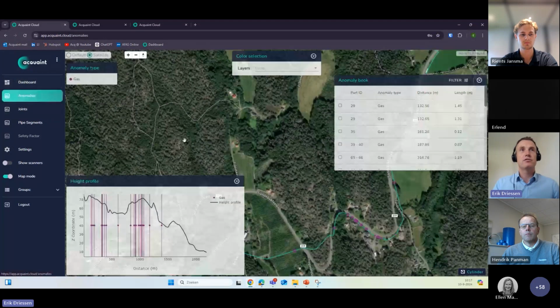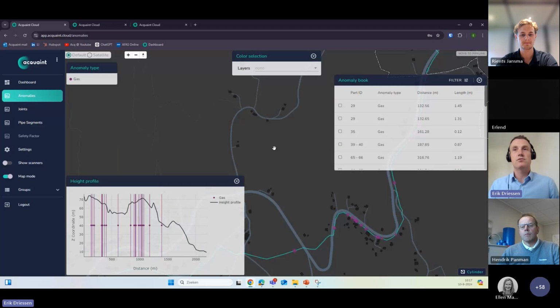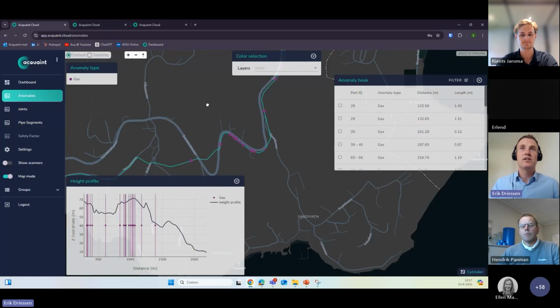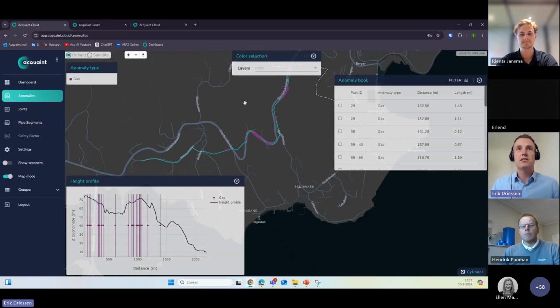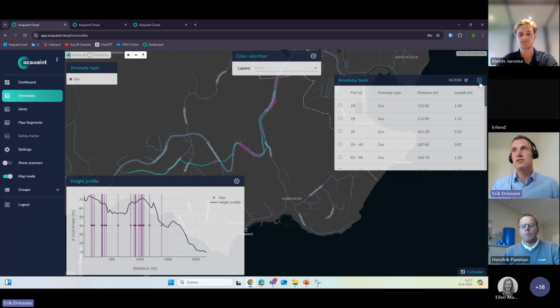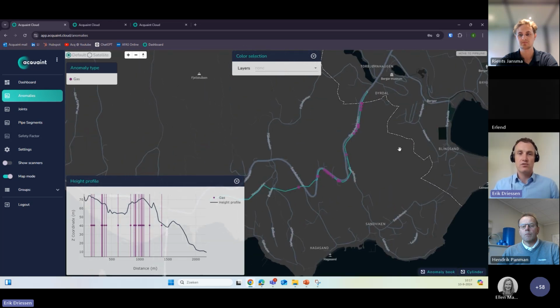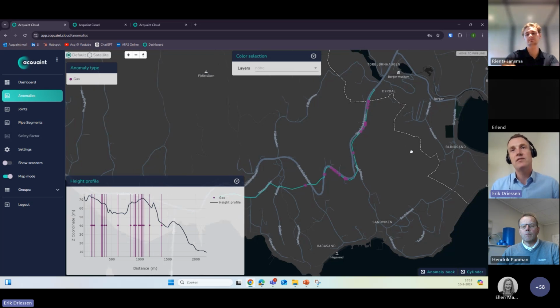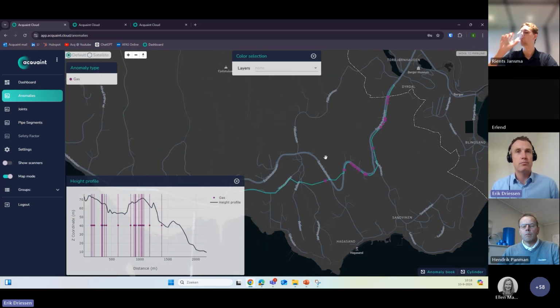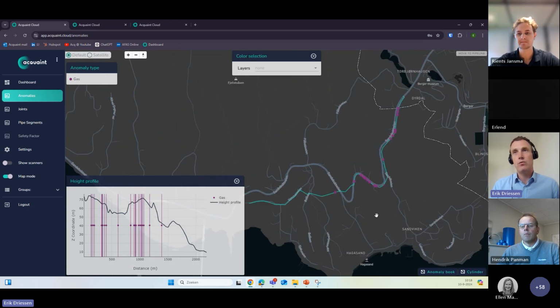So I'm now going to look at the anomalies. I will set the default mode. In this anomaly view, normally we report the most important anomalies, like pieces of cement that are missing off the liner, or if there is dirt observed somewhere in the pipeline. And actually the only anomaly that we have detected here were some gas pockets, which need some explanation, because while pigging the pipeline, there's also a risk of introducing gas into the pipeline, which we suspect has happened here.